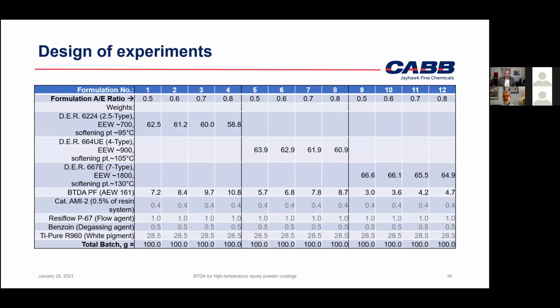Go ahead, Kevin. Yeah, people that are familiar with powder coating formulating, these are fairly boilerplate formulations. You can see the binder, the resins, of course, on the top. BTDA is our curing agent. We kept the catalyst level at a constant level, and then we got some very common further raw materials and additives.